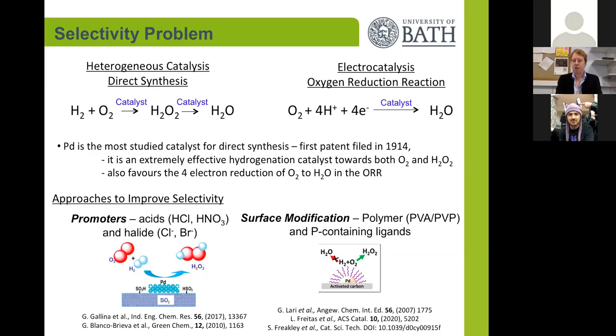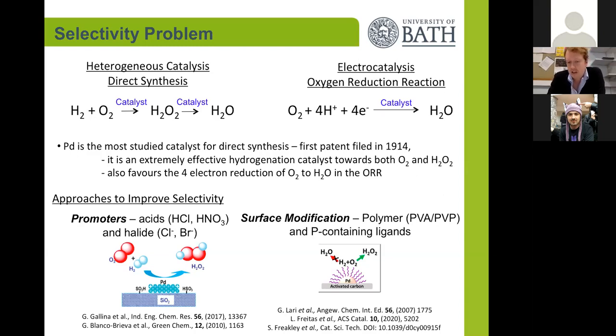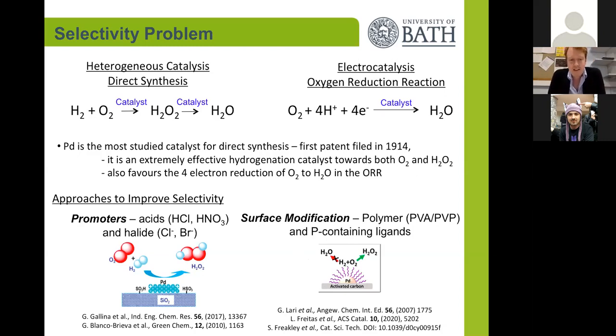Another approach to minimize the use of these promoters is to modify the surface of the palladium. This has been extensively studied using polymers such as PVA and PVP, and more recently with some phosphorus-containing ligands added to the reaction solution. This can help in a number of ways to stop the back diffusion of hydrogen peroxide through the hydrophobic layer around the palladium particle, but also poison extended palladium surfaces to prevent the O-O bond of oxygen or hydrogen peroxide from cleaving.